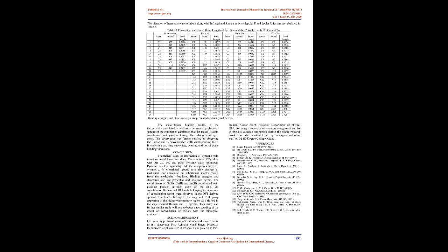The metal-ligand binding modes of the theoretically calculated as well as experimentally observed spectra of the complexes confirmed that the metal(II) atom coordinated with pyridine through the endocyclic nitrogen atom. This observation was further verified by observing the Raman and IR wave number shifts corresponding to CH stretching and ring stretching, bending, and out-of-plane bending vibrations.